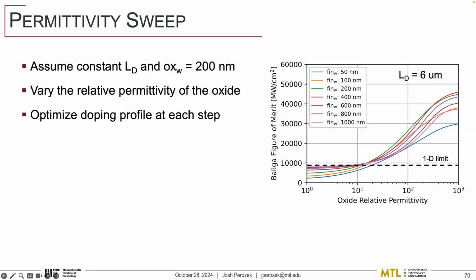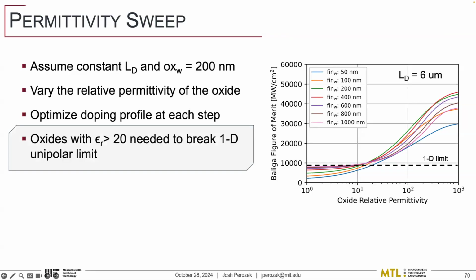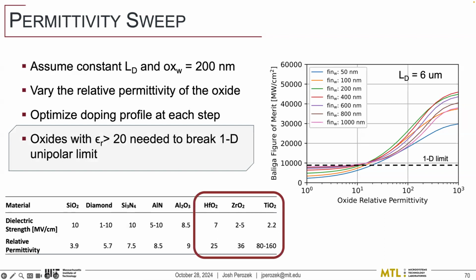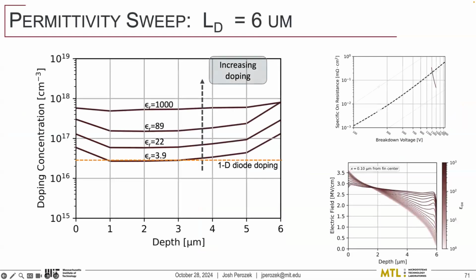But we put that as an upper bound and started looking at these and found that we only need permittivities greater than 20 to make this improve past the 1D unipolar limit. And there's plenty of materials that let us do that. We've got hafnium dioxide, zirconium dioxide, two which are used very frequently in the semiconductor space. Then we have titanium dioxide, which is a little more experimental, but has way bigger permittivity, around 100 instead of like 35 or so.